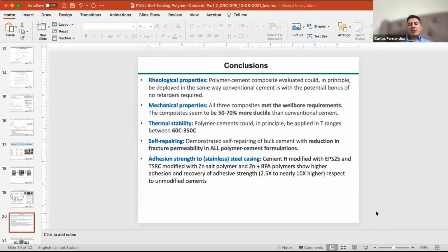So the polymers are more flexible, more ductile materials to begin with, right? So when you add that in a solid solution, which is this cement polymer composite, you will bring down the compressive strength of the material. And I will say probably also the tensile strength, although we haven't measured it. It's not a rule of thumb, but usually when you reduce the compressive strength, you see a reduction also in Young modulus. And we observe that. We observe a reduction between 50 and 70% of the Young modulus.